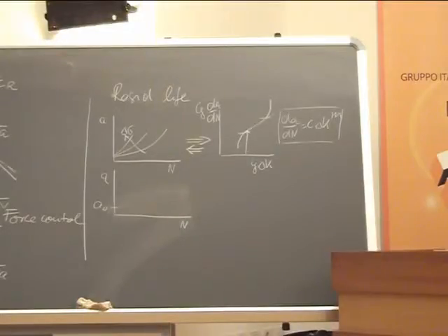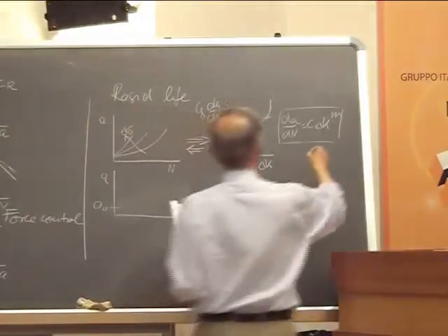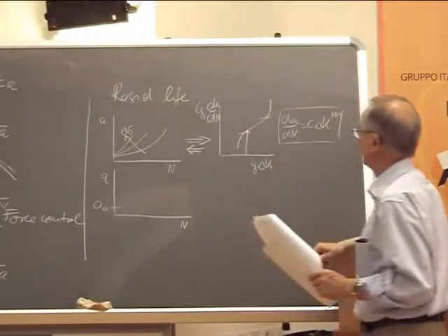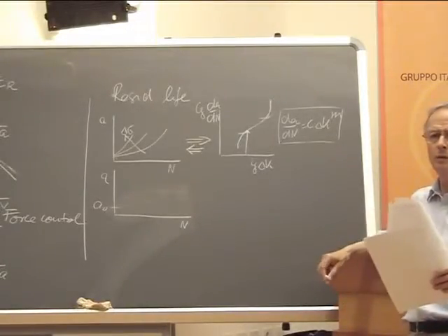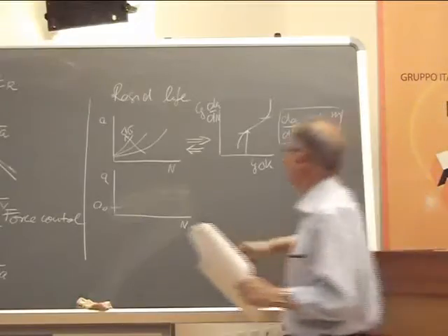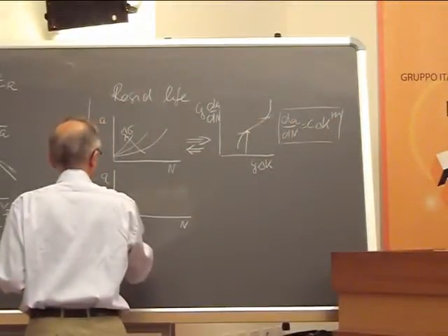We did the derivative of the a-over-N curves in order to end up with the da/dN diagram. We have to integrate the curve, of course, which for this power law, as we will see later, is still relatively easy, but when you have a more complex equation, we have to do it numerically. Okay? So we reconstruct the curve